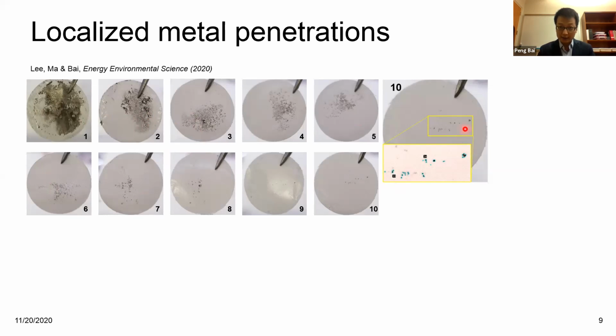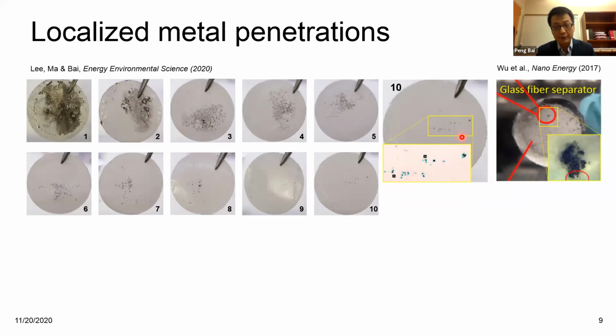And if you characterize the penetration area on the final separator, it's actually very small, right? It occupies a teeny portion of the total geometric area. And this is not only true for our commercial separator. It also happens for glass fiber separators. You can see here for this very large glass separator, you only have a little black dot. This is the dendrite penetration. Well, it may not be dendrite. It is the metal penetration.